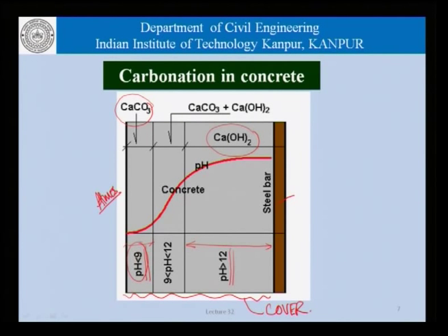Between these two zones, we have a transition zone here where the pH is, let us say, between 9 and 12, and here we have both some amount of calcium carbonate which has been formed, and not all calcium hydroxide has been consumed, and therefore, we have some calcium hydroxide there as well. Please remember that this is only a schematic representation to help us understand the carbonation process.